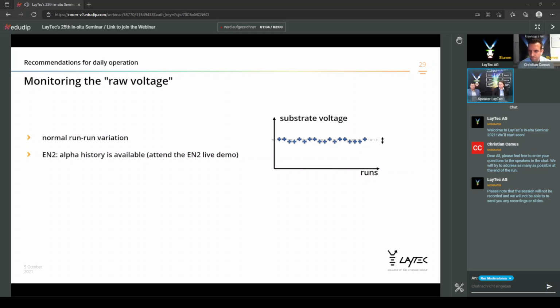And what I have got reported from my production team when they do the recalibration of the absolute is that it's sometimes very dusty, and this will happen. This will influence your measurement very strongly. I have seen several degrees C, and I think this will set your product very, very strongly off.